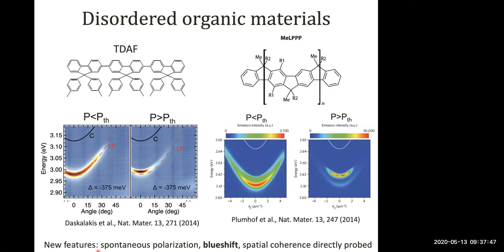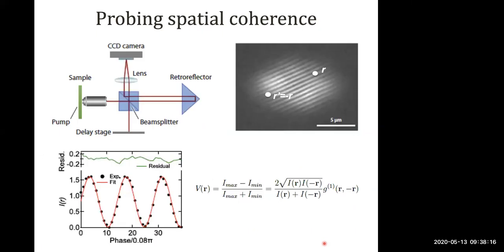In TDAF, we also were able to see the spontaneous polarization of the emission. And this wasn't possible in anthracene because the anthracene emission, due to the crystal structure, is always polarized. So there was no chance for this spontaneous polarization to be observed. Okay? And in these two systems, also the spatial coherence was directly probed. So beyond the reduction in K space that tells you have increased spatial coherence, these were also measured in real space using interferometry.